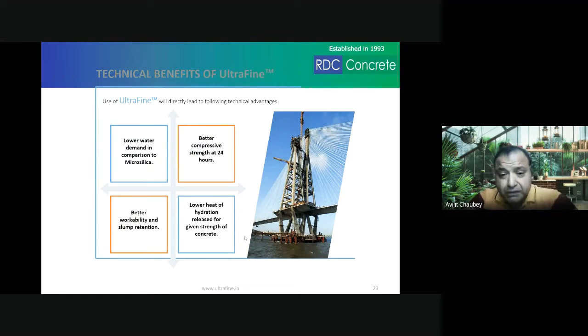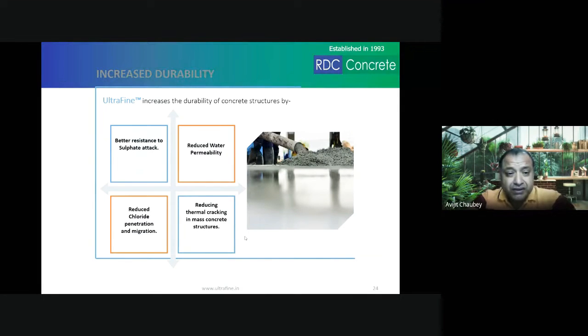Here you also get much better strength at 24 hours, better workability and slump retention, lower heat of hydration for a given strength of concrete. It has better resistance to sulfate attack, reduced chloride penetration and migration. Now, one thing, let me clarify.